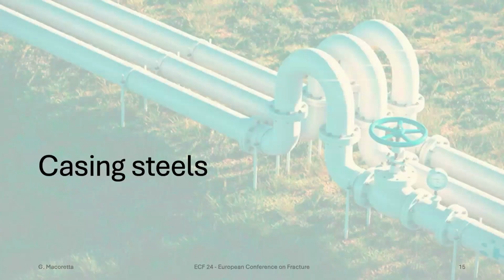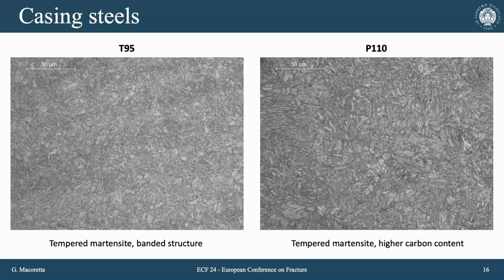If we look at what happened with the casing steels, T95 and P110, and observe the microstructure, we see that in this case too we dealt with defect-free material with a standard tempered martensite microstructure that changes a bit between the two materials, depending on the carbon content, and a bit on the treatment the materials were subjected to.